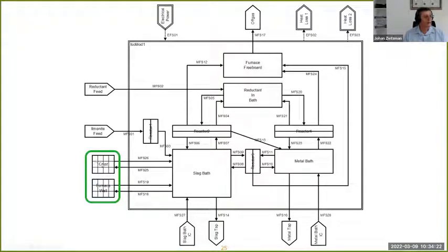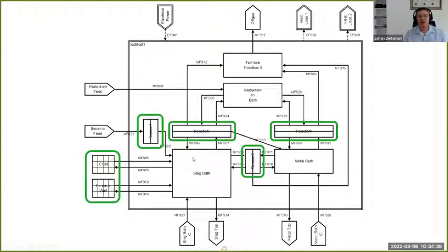The crust model is useful when you want to allow the bath to crust over when you switch off the furnace. We can see how the crust on the bath surface grows, and that also has an influence on the process. And the full thermochemical description that I spoke of is that all of these little reactors are driven through equilibrium calculations with FactSage data and ChemApp equilibrium calculations. So this is a pretty sophisticated, dynamic description of an open bath smelting process.